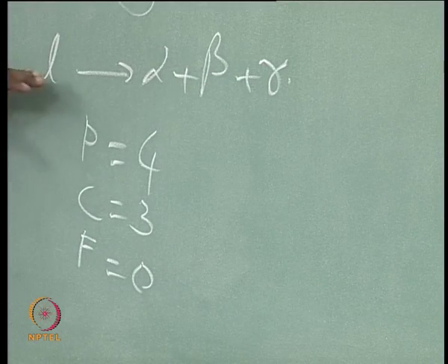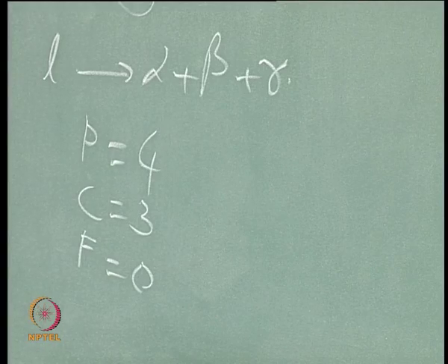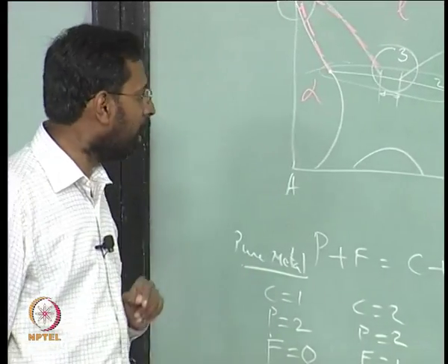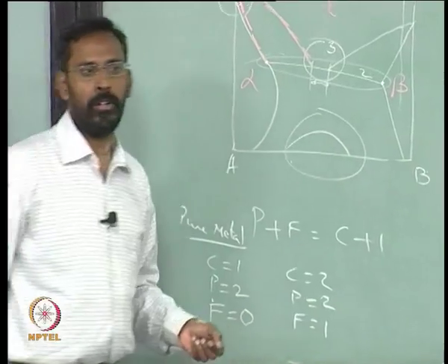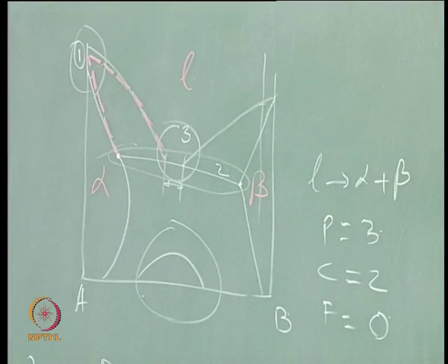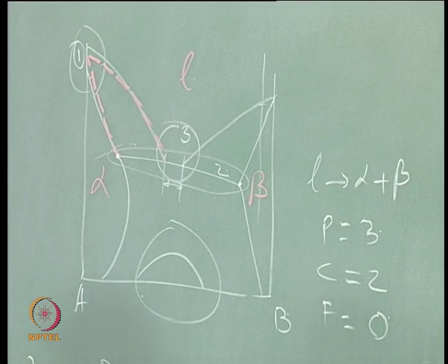Okay. So, this is something which one has to remember. So, that is the third one. Then there is a fourth issue which comes with respect to this. You see a miscibility gap there. The miscibility gap basically means that a one phase is splitting into two phases, is not it? A one phase splitting into two phases means a miscibility gap should always be enclosed in a single phase domain only. You cannot talk of a miscibility gap in a two phase domain.